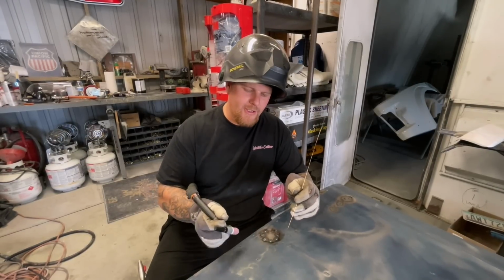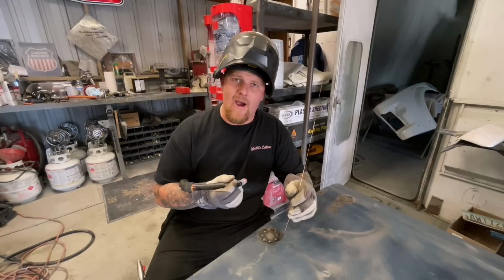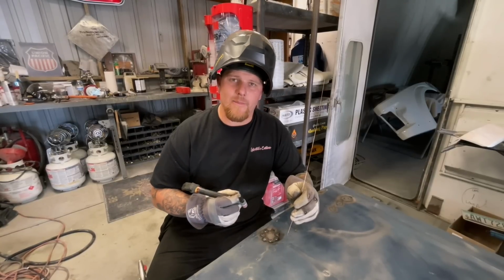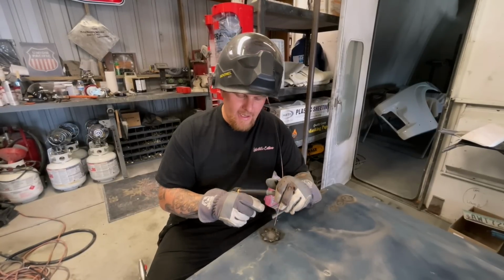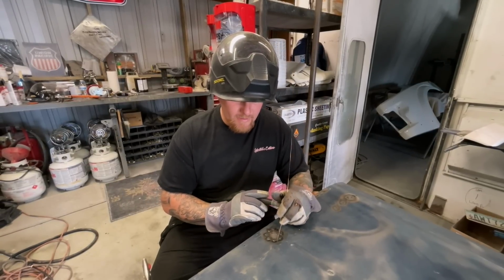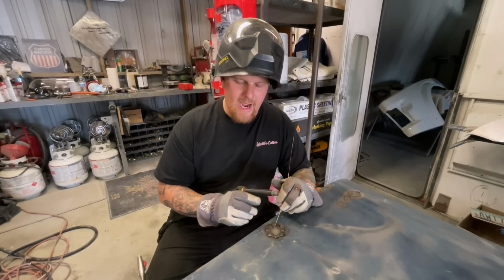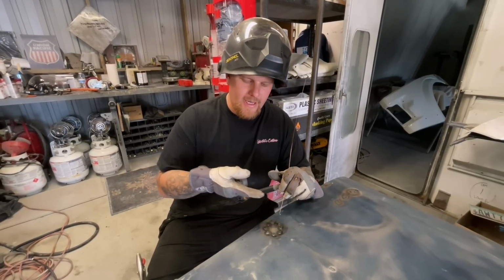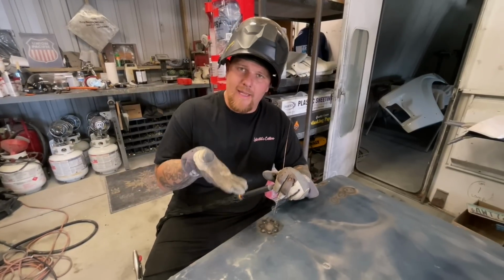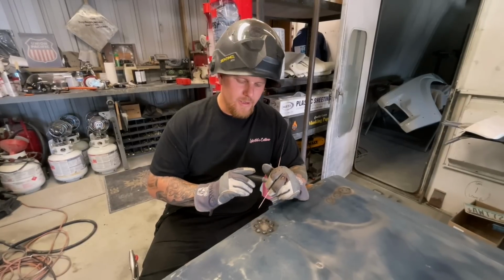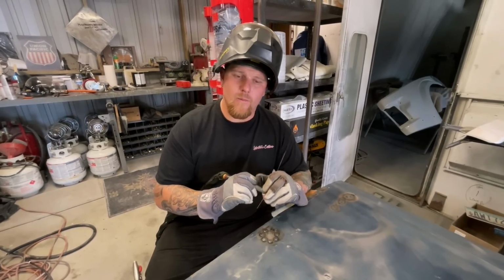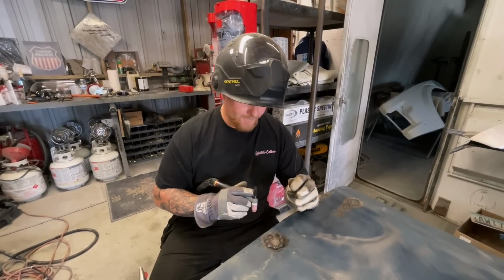The whole goal here is you're getting in with the heat and you're getting out. You're not sitting there for a long period of time. You can see here the heat affected zone is very small, and that way you only have to hammer and dolly that area to bring that weld back up. So we're gonna go through and weld this thing continually around.